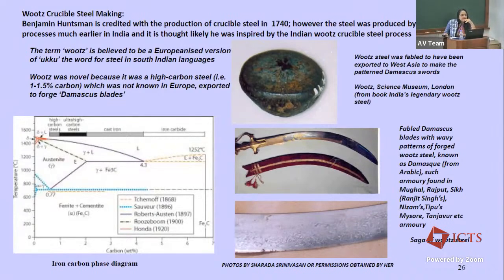Now, what is this Wootz steel? So Wootz is believed to be a Europeanized version of the term ukku, the word for steel in South Indian languages. And the novelty is that, now when I talk about wrought iron, that hardly had any carbon in it. It must have had carbon which is less than about 0.04%. So that iron could have been forged. But what happens when the carbon content keeps increasing is that it becomes steel, and that makes it harder. And so it was used for weapons and so on. But normally the kinds of steel that were used were what were called mild steels with about 0.04% carbon or so. But what was novel about Wootz is that it had a composition of about 1.5% carbon, which was not much used in the European world.